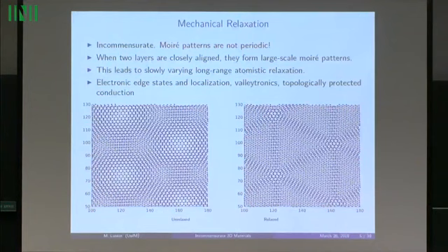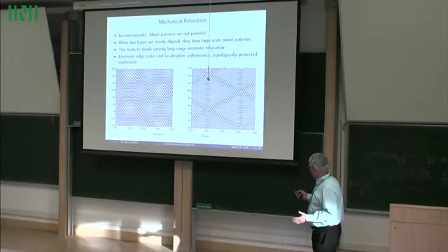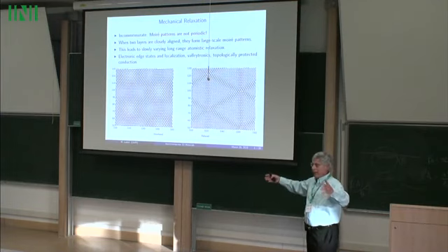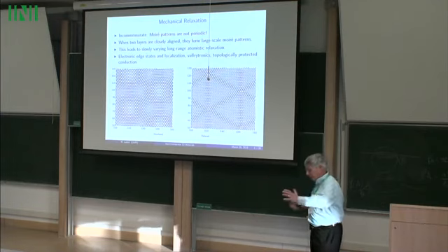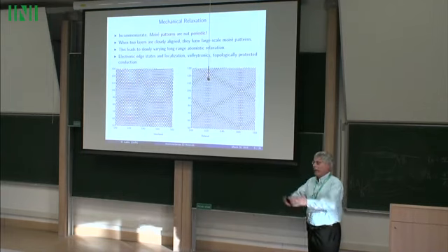Exactly. Well, are you saying the layers will actually merge into one layer? No, he's saying they'll be periodic with hexagonal symmetry. Oh, because there's a twist to it. There's an imposed twist on this. So this is part of a large material that can't untwist. To get to what you're saying, which would be the energy minimizing state, you'd have to untwist globally.